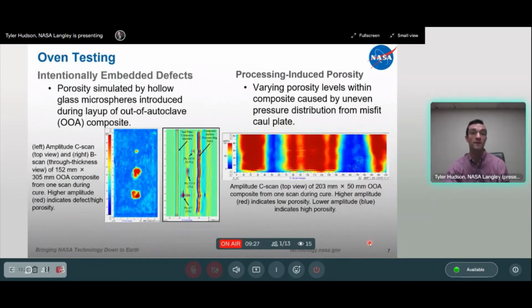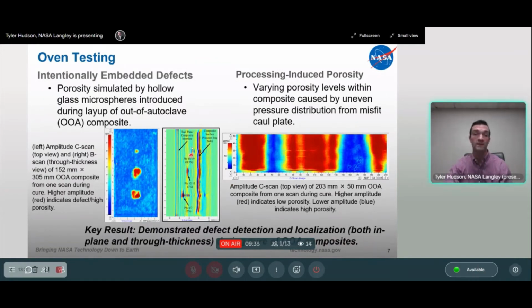We also did oven testing, and primarily the reason I'm showing this slide is for two reasons. So one, this image here shows clearly that you can not only determine where a defect is spatially, but also through the thickness. So this is one surface of the composite. This is the other surface of the composite. And then you can see these three defects at varying thickness. This is about 25% of the way through, right at the mid plane, and then 75% of the way through the thickness. And this is done on out of autoclave composites, and most wind turbine blades are made with out of autoclave